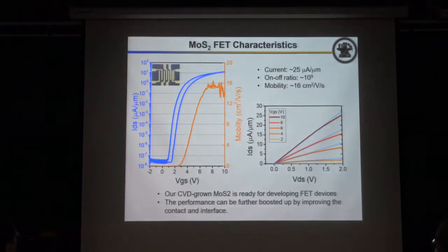We also use our 2D CVD material to fabricate FET. Well, this is a typical example. And as you can see, the mobility is about 10 to 20 for MoS2. But for WS2 it is much higher, maybe 30 to 100. And the current on-off ratio is also very high, up to 9 orders of magnitude.